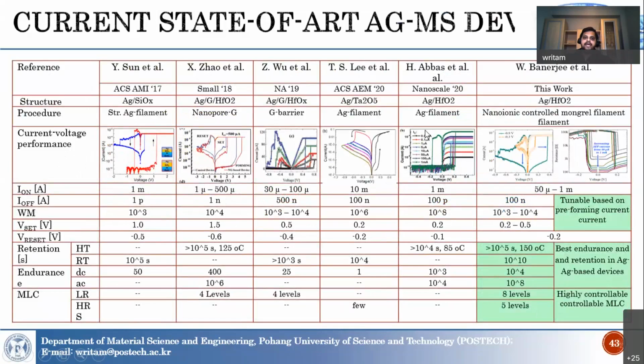Okay, so here is the overall summary of the memory behavior and how it looks like. You can see all silver-based devices with different kinds of switching matrices. But in this case, we have a very stable memory switching behavior, and it is a very much tunable resistance state based on the preforming condition. So far we have achieved the best endurance and retention behavior for silver-based devices, and we have highly controllable multi-level switching behavior for silver-based devices.